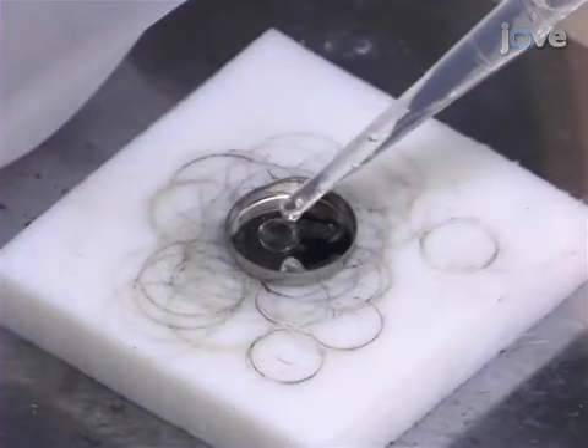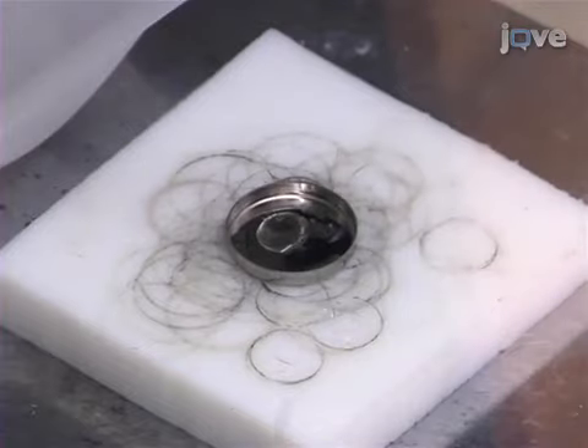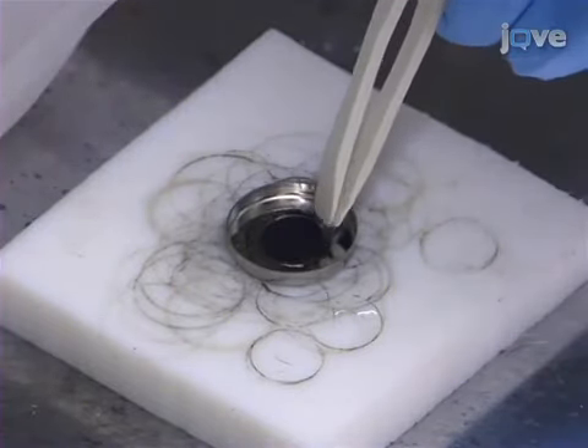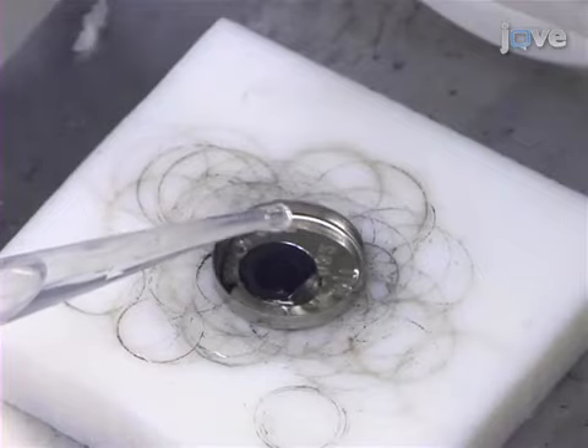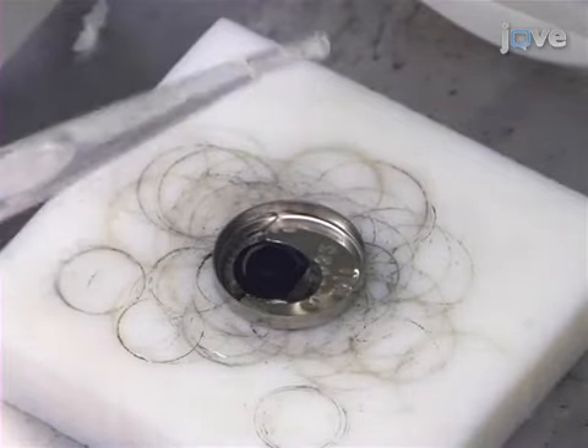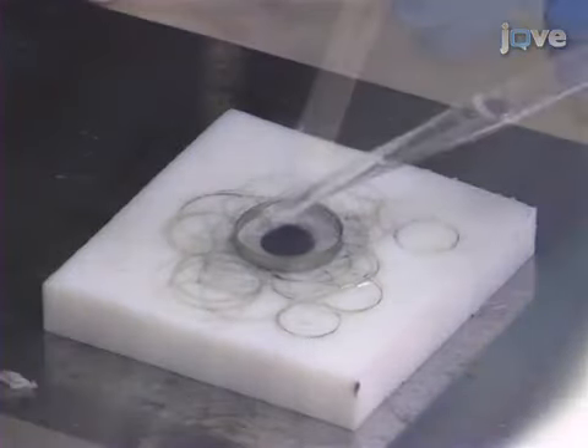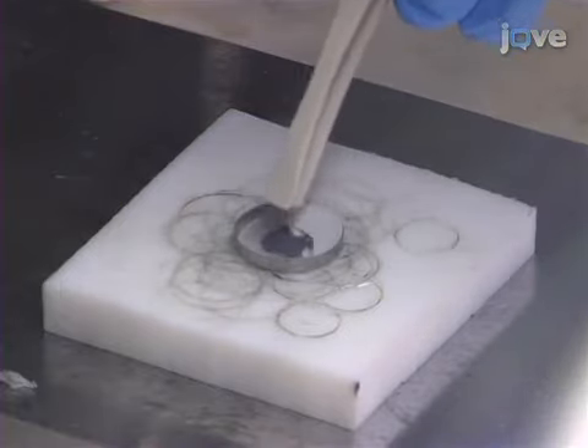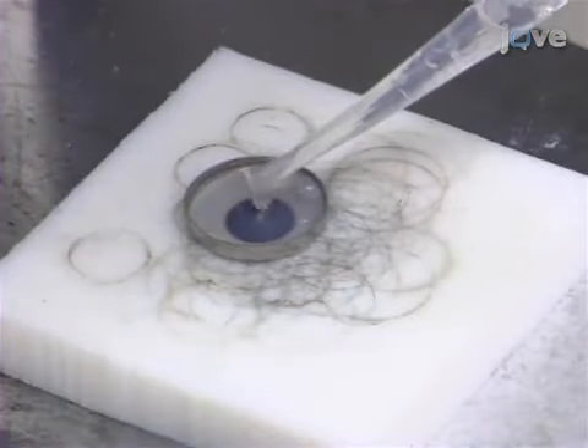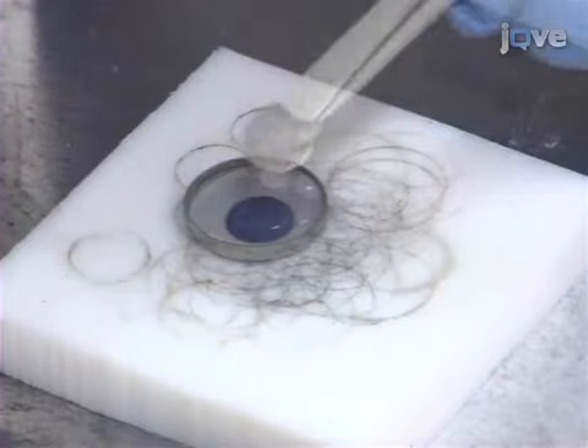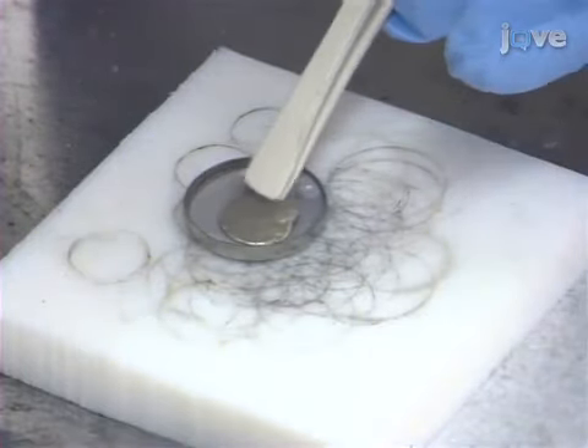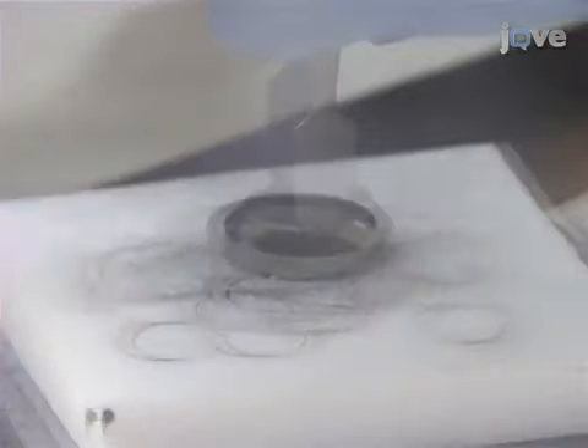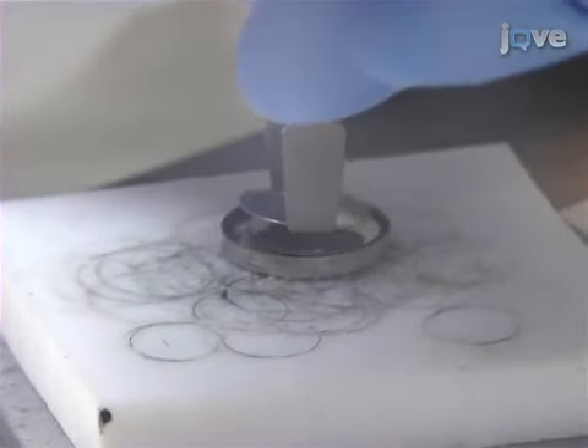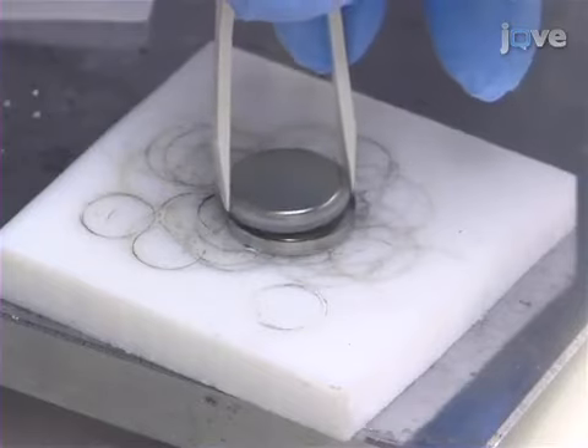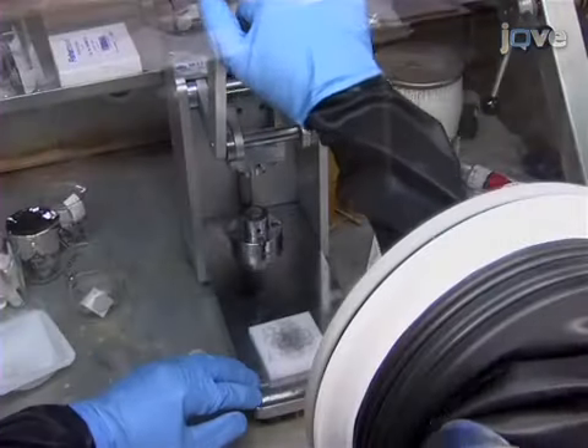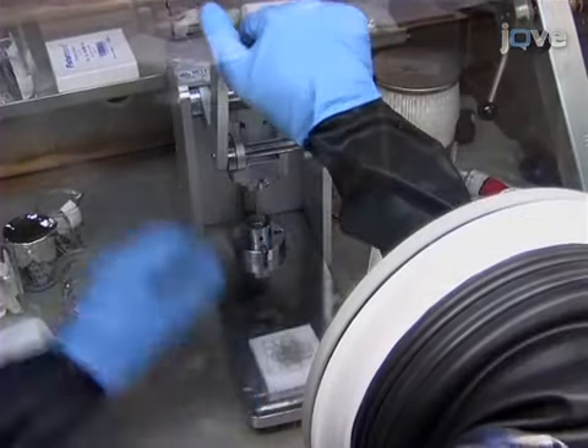To start assembly, add 2 drops of the electrolyte onto the cell cup and position the working electrode. Next, add 3 drops of the electrolyte and place 2 separators with 2 drops of electrolyte between them. Proceed to add 2 more drops of the electrolyte and position the lithium counterelectrode. Now, place the 2 stainless steel spacers and a spring on the lithium disc. Finally, close with the cell cap and crimp the cell 3 to 4 times.